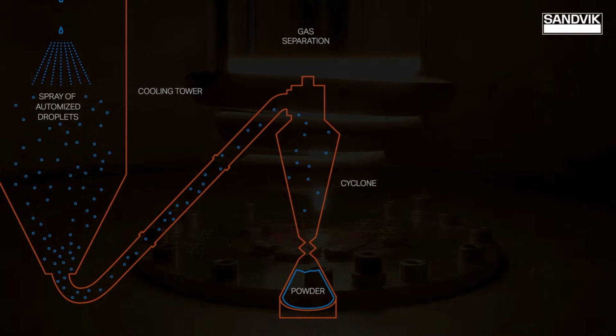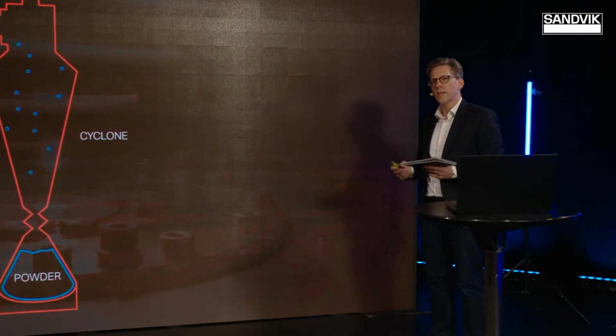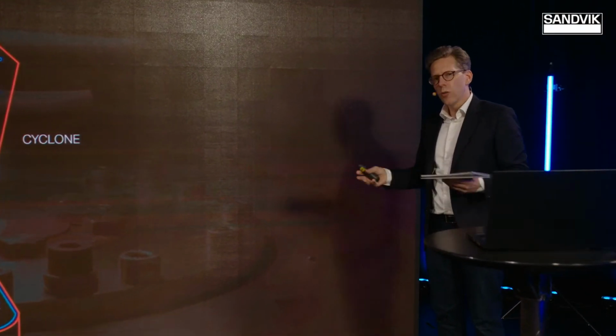And related to that, we also have a packing station that is under inert gas condition, and also the entire production line here, including the sizing, also has inert gas to protect the titanium from any oxygen pickup or cross-contamination. We don't want that.